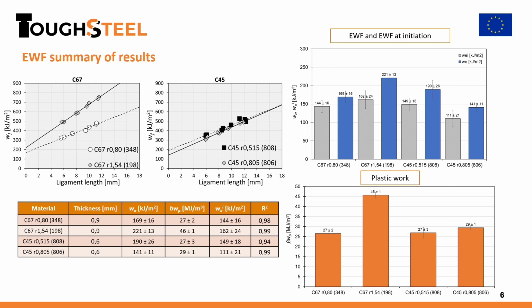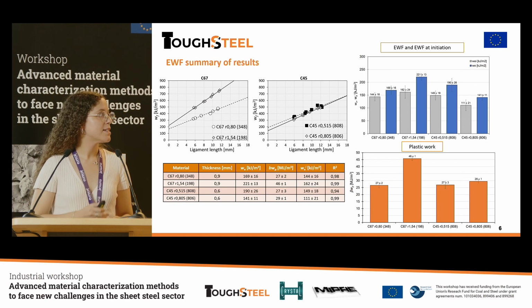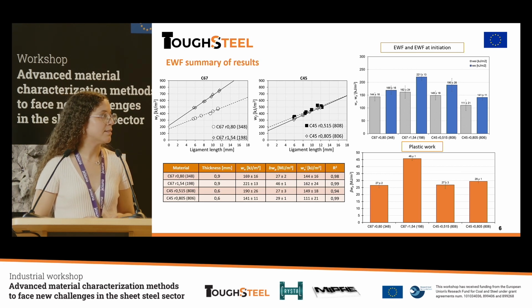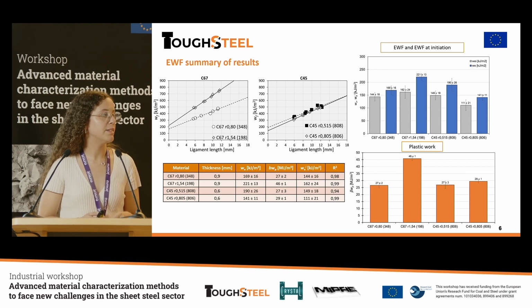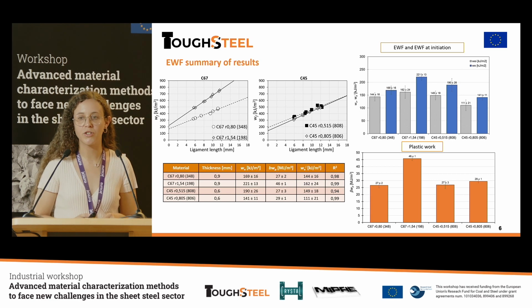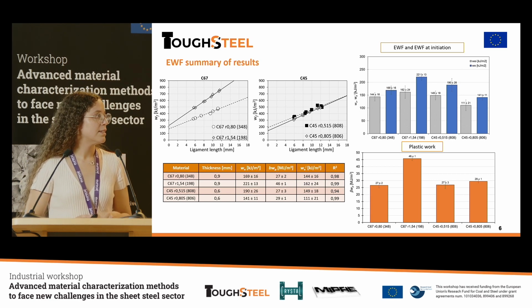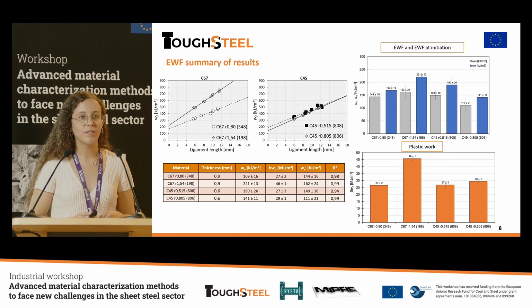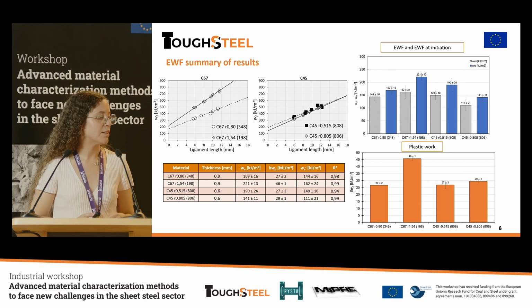Next, we can see here the results that we got for these materials. We have separated them into C67 and C45. And we can see, for example, in C67 that the values for the essential work of fracture were quite different, in this case only by changing the anisotropy of this material. In the case of lower anisotropy, the essential work of fracture value was lower than for the other case. In the material C45, we found that the results were similar, although in this case, the material with lower anisotropy showed a little higher essential work of fracture values.